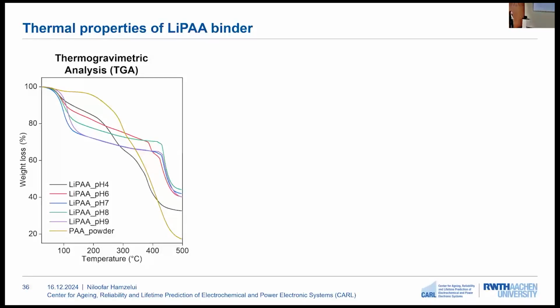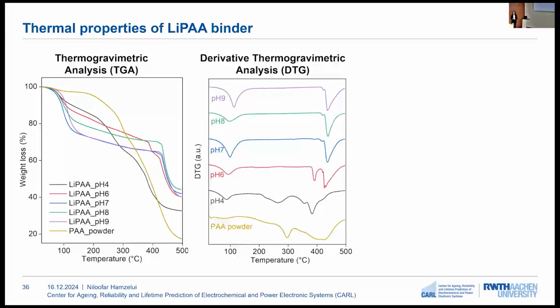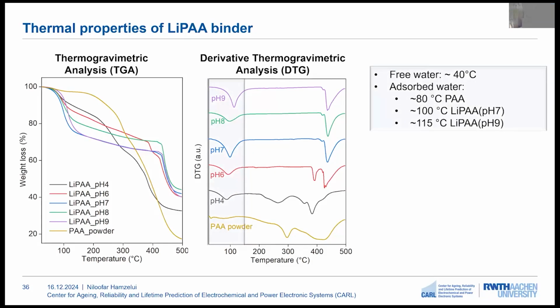The thermal properties of the binders were investigated using thermogravimetric analysis, or TGA. Here, the weight of the sample was measured depending on the temperature, and afterwards the first derivative of the thermogravimetric analysis, the DTG curve, was calculated for the PAA powder and LiPAA with different pH of 4, 6, 7, 8, and 9. Based on this graph, in the first region we see a peak at 40 degrees due to free water, and the peak due to absorbed water is seen at 80 degrees for PAA, and this value increases to 115 degrees for the LiPAA with a more basic pH.